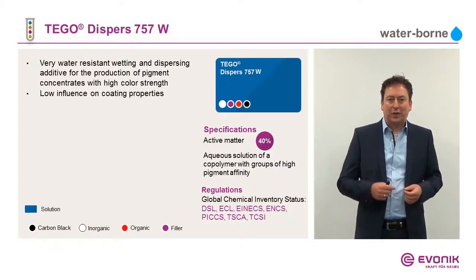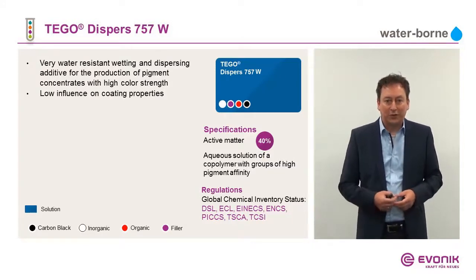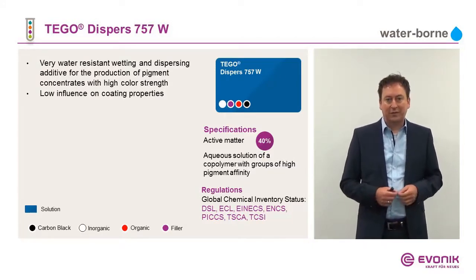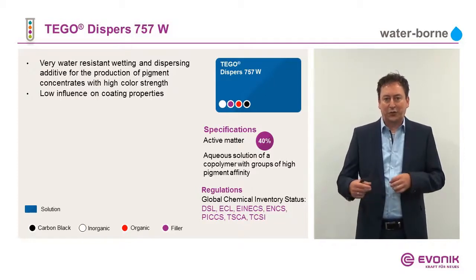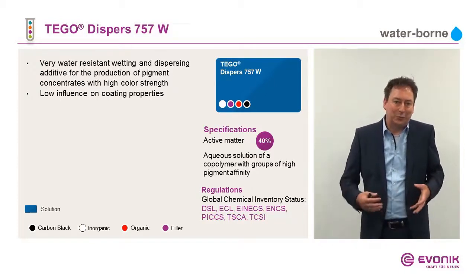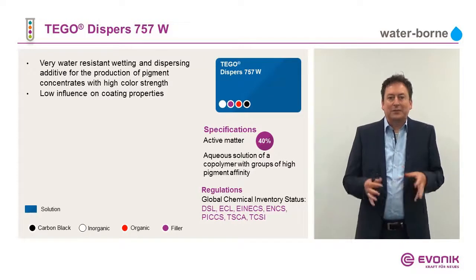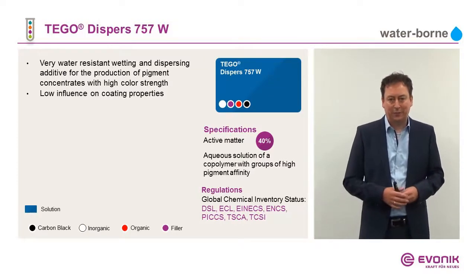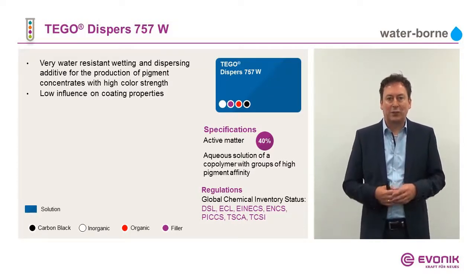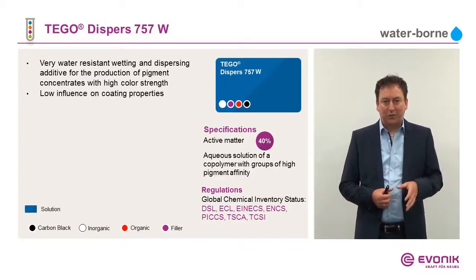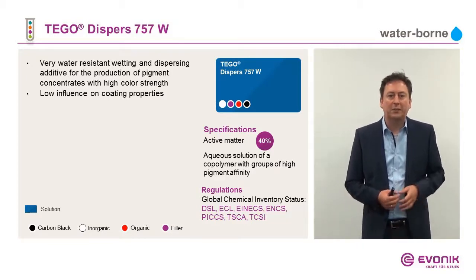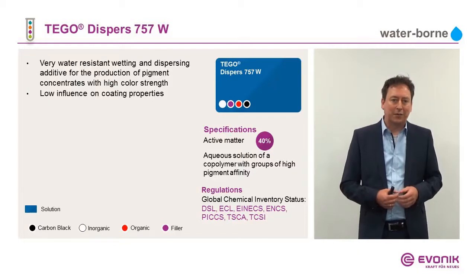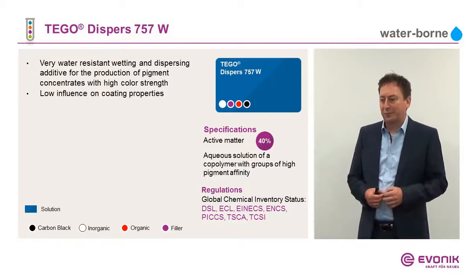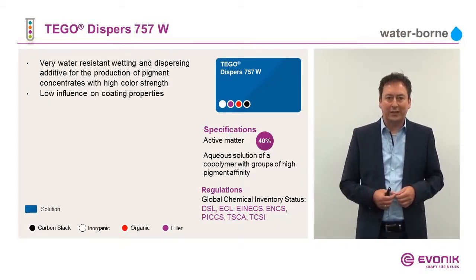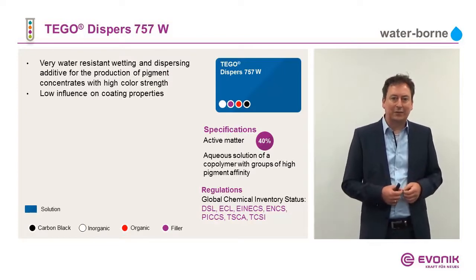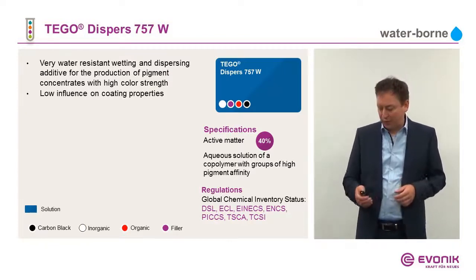Problem is that the neutralizer can evaporate during the grinding, and so the 757W gets water insoluble, and then you block the mill. So that means the customer has to watch the pH value of the grind very carefully. So you have to make sure that you work all the time in alkaline environment. So in pH values higher than 7. Then the 757 gives outstanding